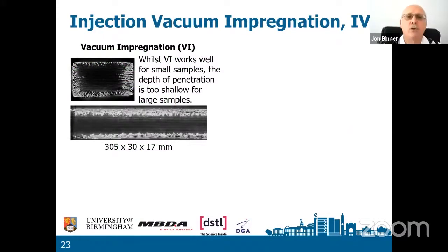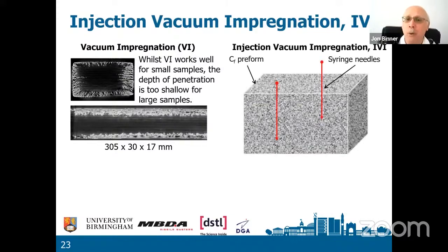Originally in the laboratory, we used vacuum impregnation, and it worked extremely well for small samples. But as soon as we started to make our samples bigger, we found that vacuum impregnation didn't work. You got that very shallow depth of penetration. These are micro CT, X-ray microcomputer tomography images, and you can see how only the surface layers have got the material deposited. So we needed to find a new approach.